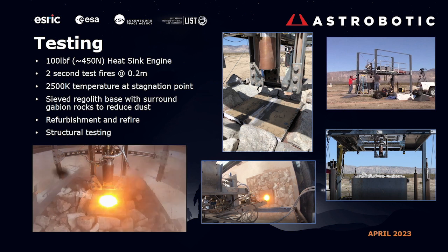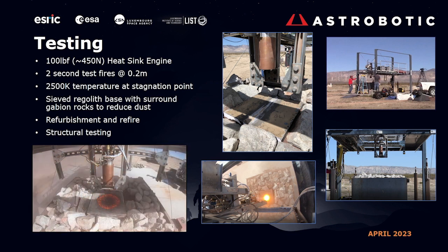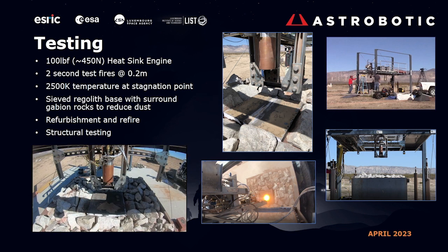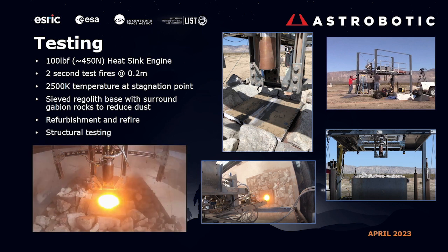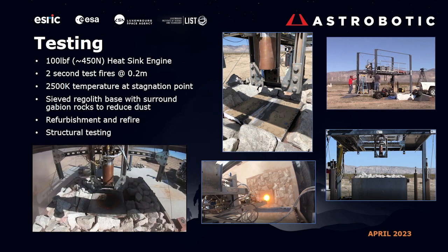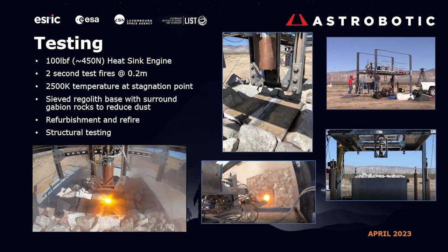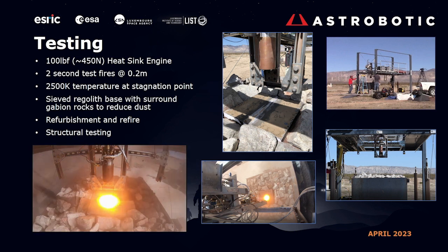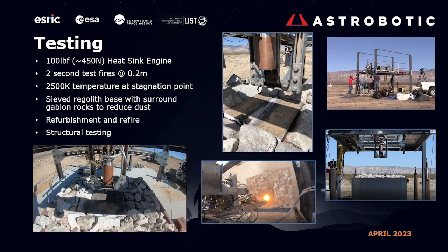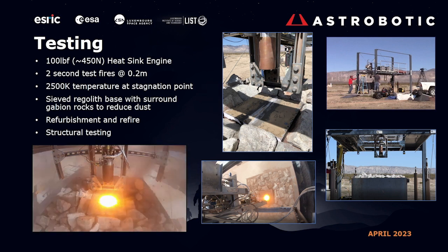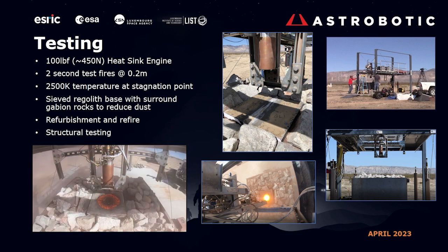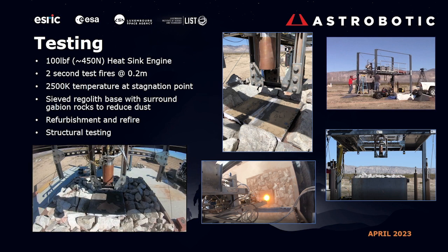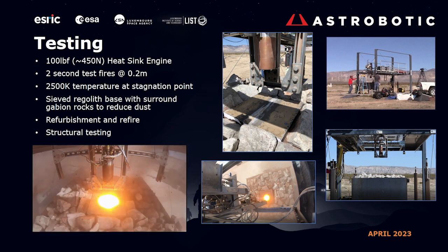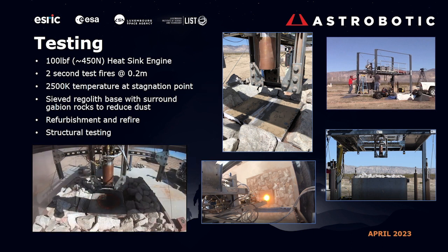So we created these test pads, and with a significantly smaller methane rocket engine than we just saw, we're able to test them and validate that this material, after off-gassing, was able to sustain a landing rocket situation. So it's about a 450 Newton engine firing for 2 seconds at a very close distance.